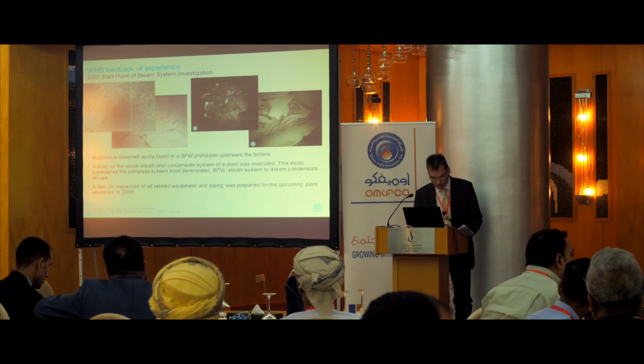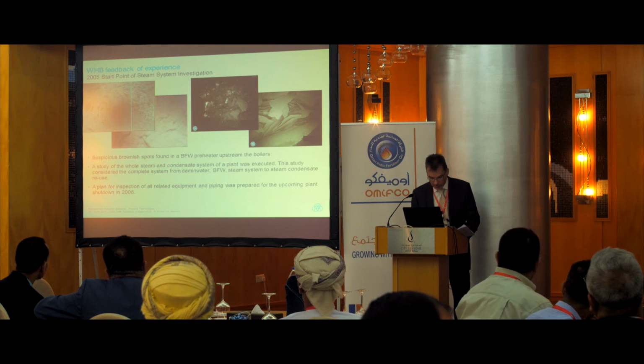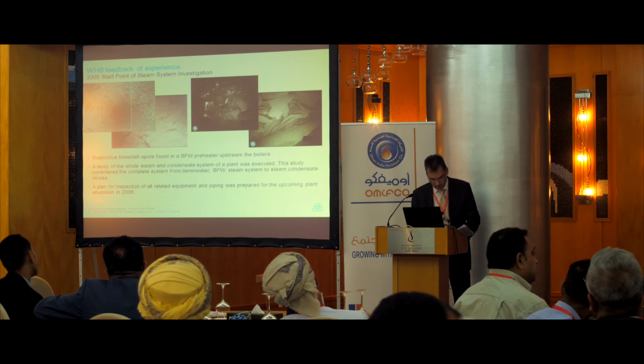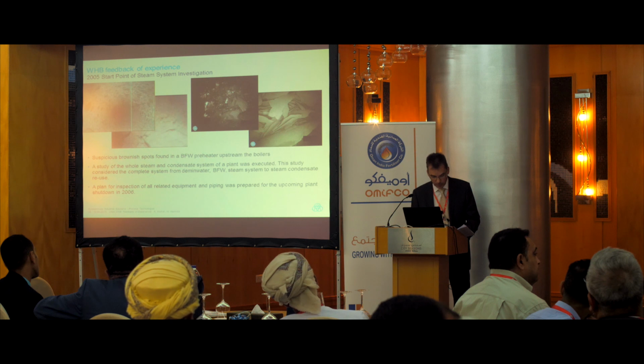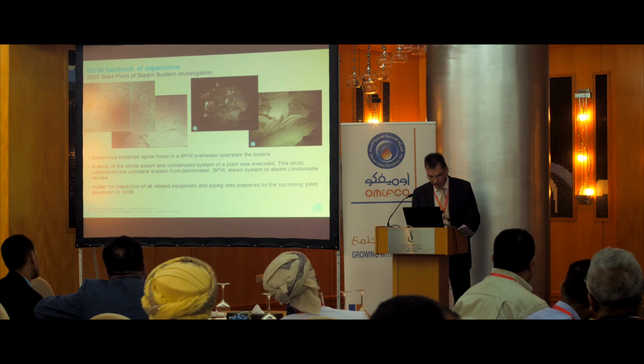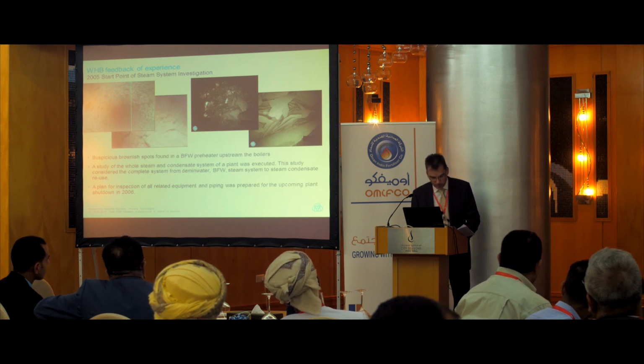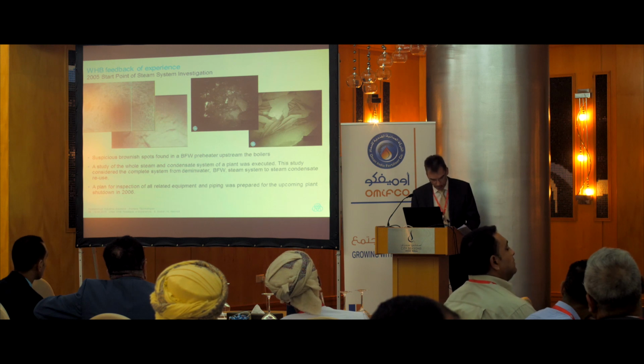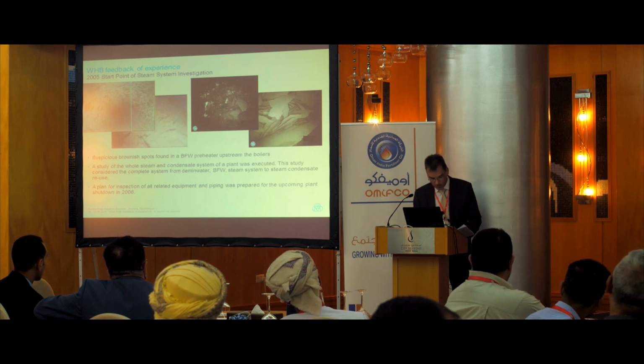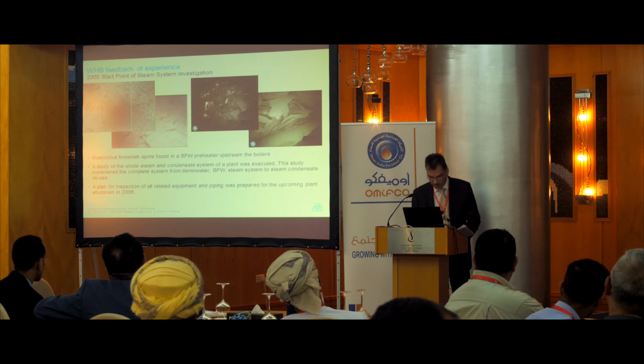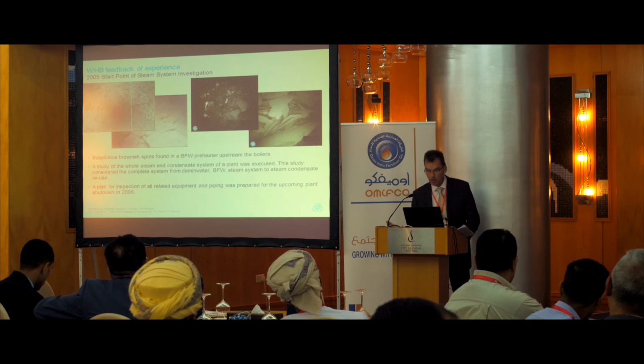Finally, a steam condensate line has been identified to be a possible source for these iron deposits. This line was then rerouted from ending in the deaerator to now ending at the water makeup unit for treatment before reuse again. Also, recommendations were given to raise the pH value to 9.5 and to limit the dosing of oxygen scavenger, depending, of course, on remaining oxygen in the boiler feed water coming out of the deaerator.